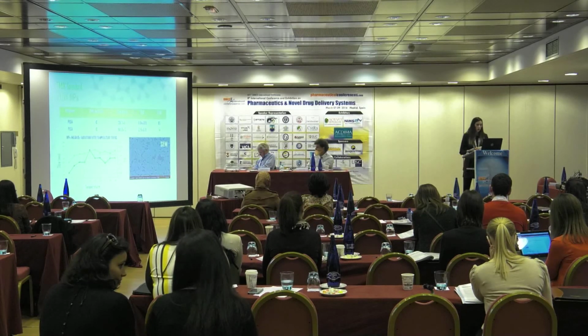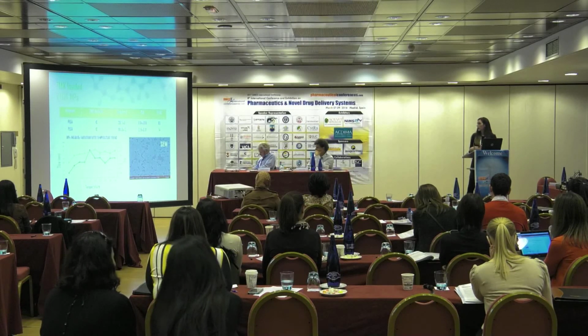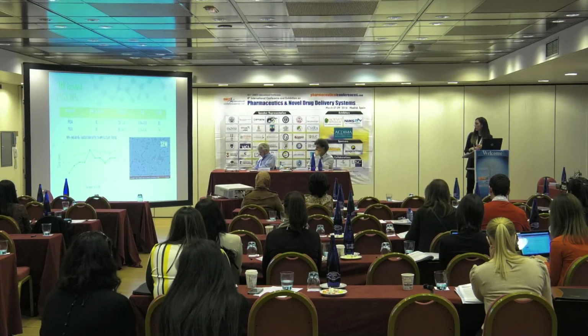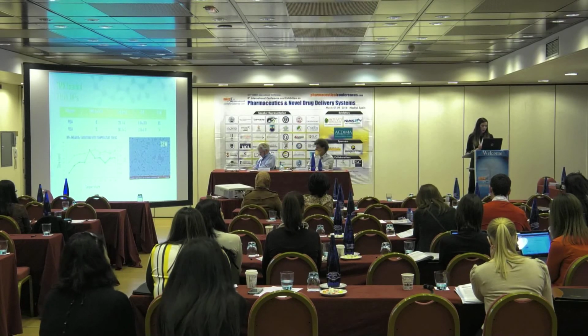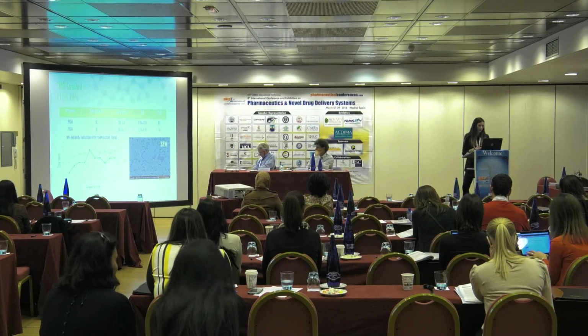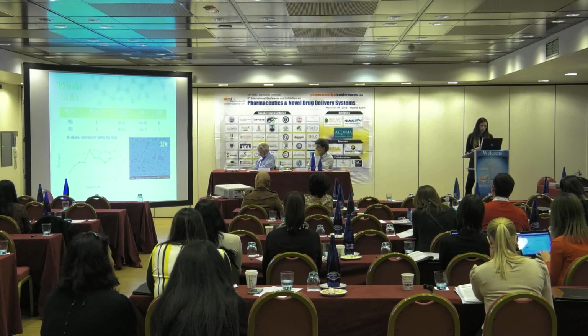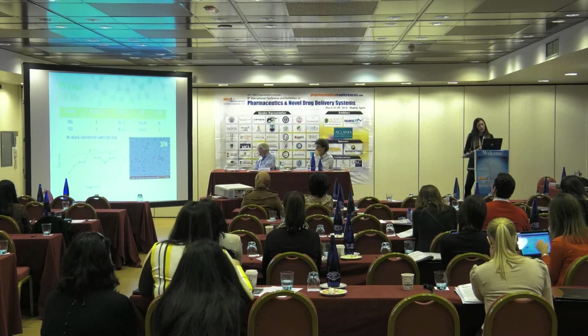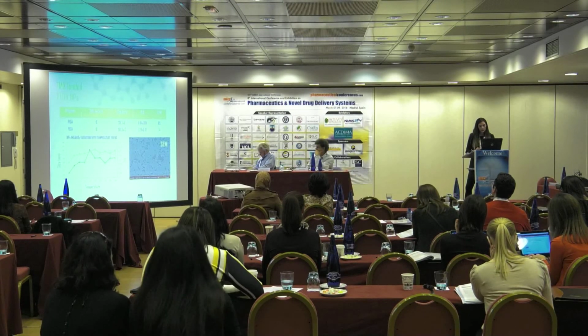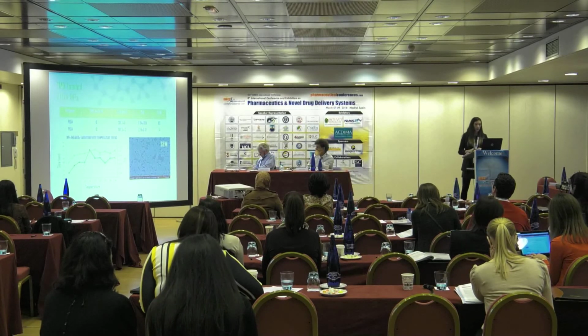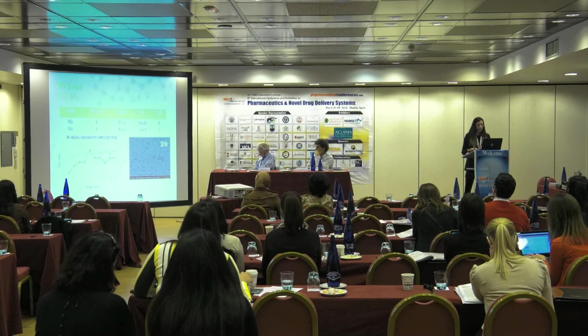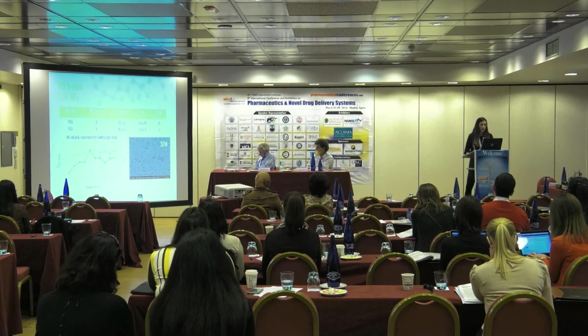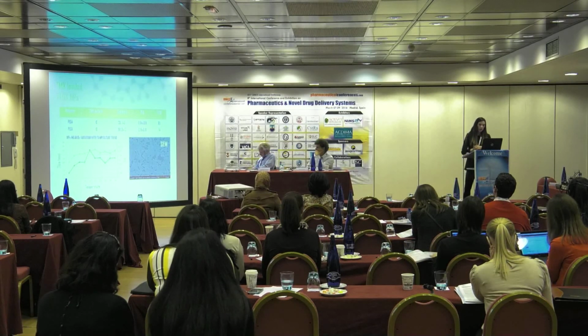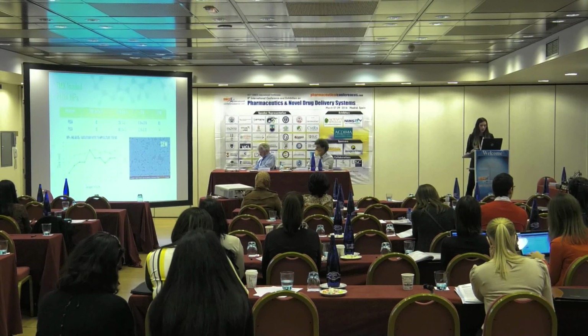Another interesting thing that we did is to take our freeze-dried particles, resuspend them and test them versus temperature, to see how these particles behave at the temperatures that we can find in the biological environment. And we see that although the size changed a little bit, this difference in size does not reach 10%. So for our resuspension, it's pretty good. And the polydispersity is also good because we don't have a really high variation. And as you can see in the scanning electron microscope images, the shape is always spherical, and we can also confirm the narrow size distribution.